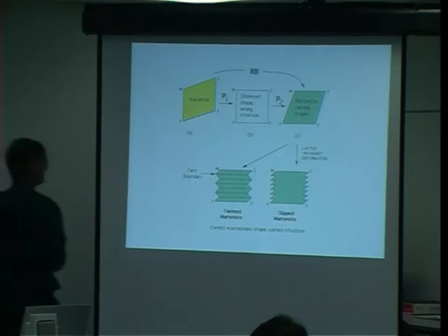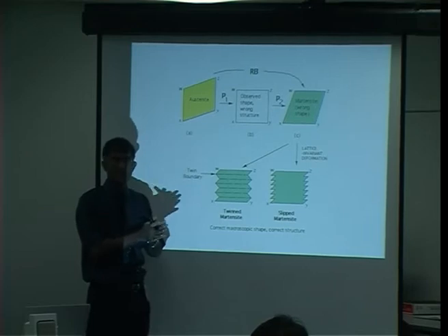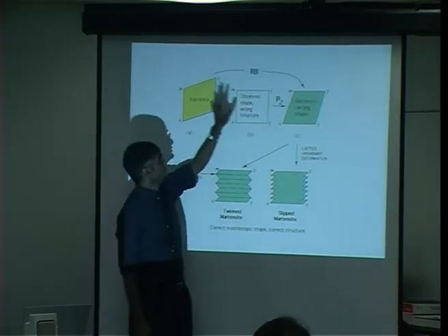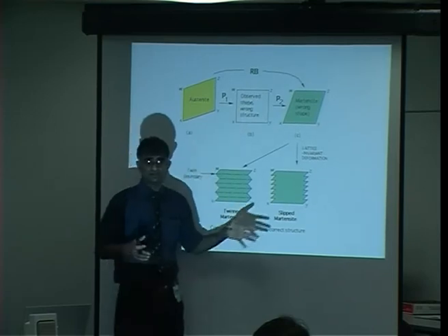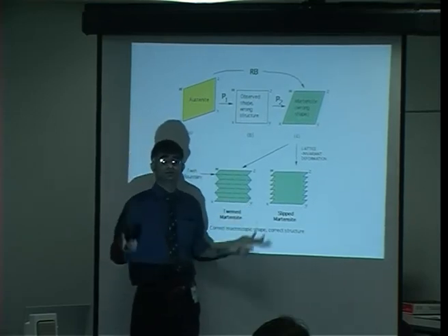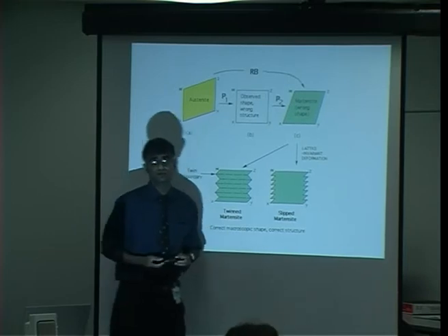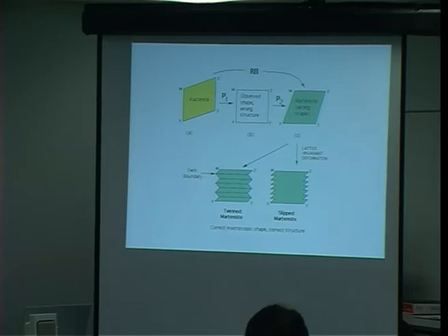The orientation relationship will be exactly that the close-packed planes are perfectly parallel, and close-packed directions within those planes are perfectly parallel. So in this case, we stop over here, because the strain which transforms austenite into hexagonal iron is a shear deformation. It's not a more complicated deformation like an invariant line strain. So why don't we get more of epsilon martensite happening? Yeah. So it would be energetically more favorable. It's completely to do with energy.